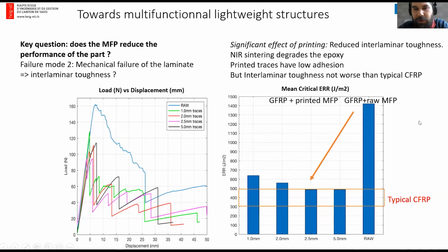This is lower because we have to sinter the silver ink. These are nanoparticles that have to be sintered at high temperature, and we have observed that it slightly degrades the epoxy and lowers the adhesion also. The printed traces have also shown that they are not sticking very well, so they are like weak spots in the structure. However, this critical energy release rate is still better than the typical toughness of a CFRP laminate. So it's not really a weak point overall.